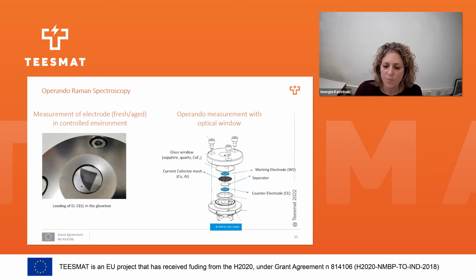And at the top we seal it with a glass window, and we have different kinds of windows depending on the kind of measurement we want to take, and also we have to know that this material will not react with the electrolyte. And once we seal it, there is an open hole that we can use to put in our electrolyte.